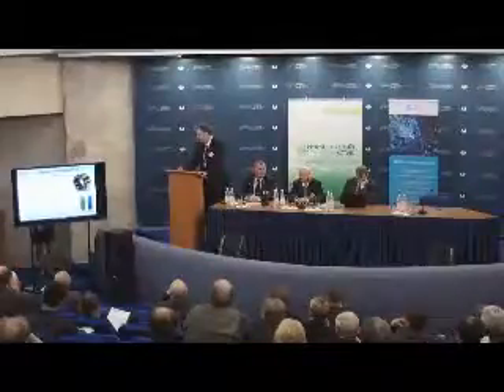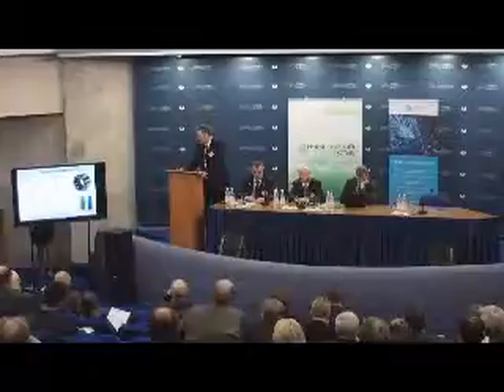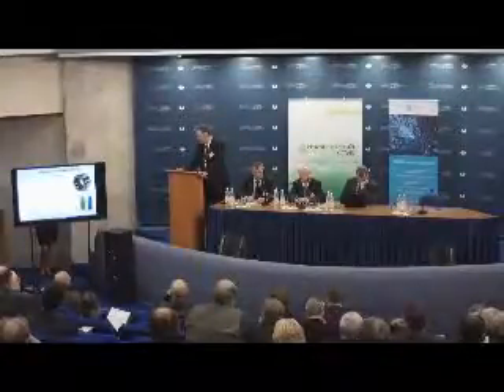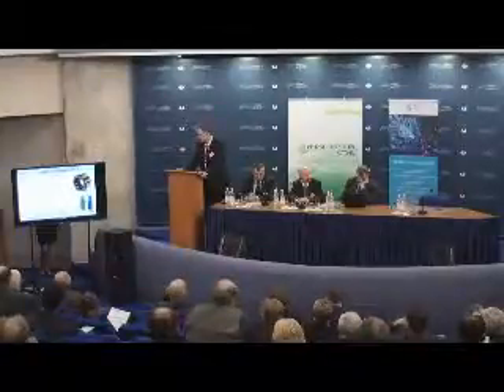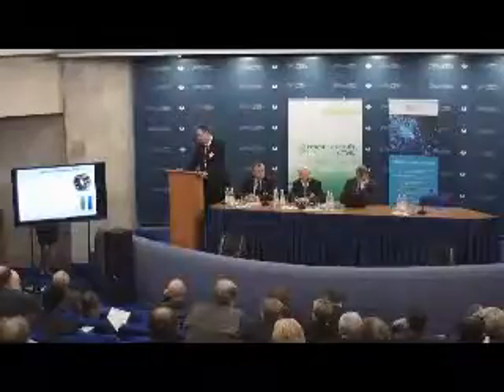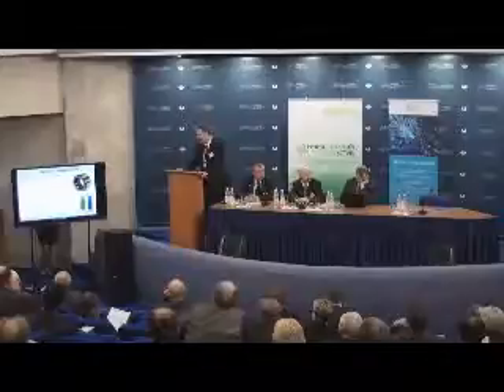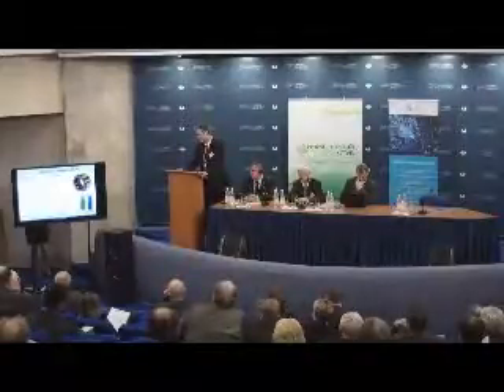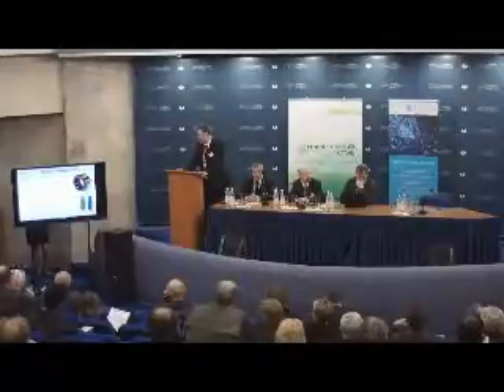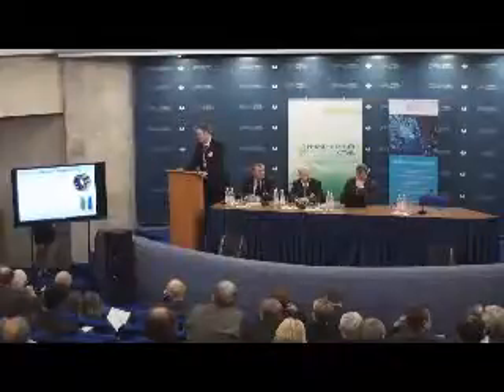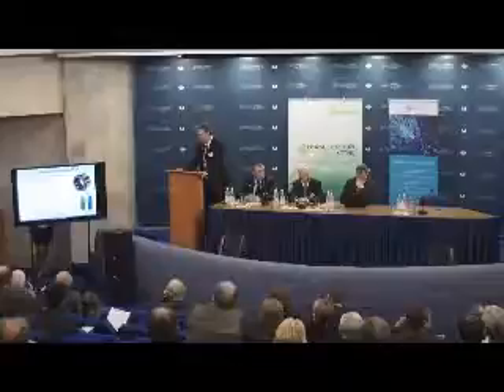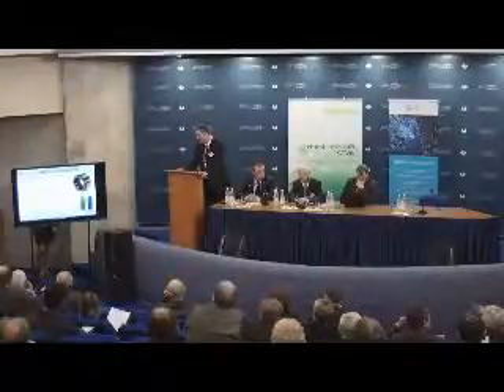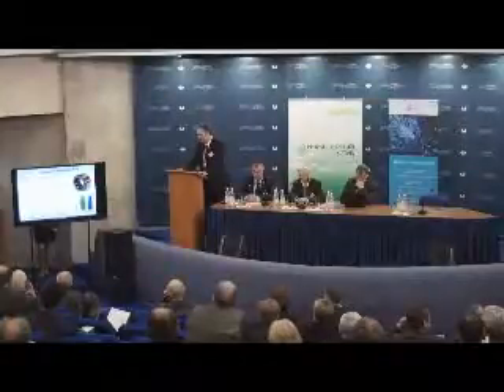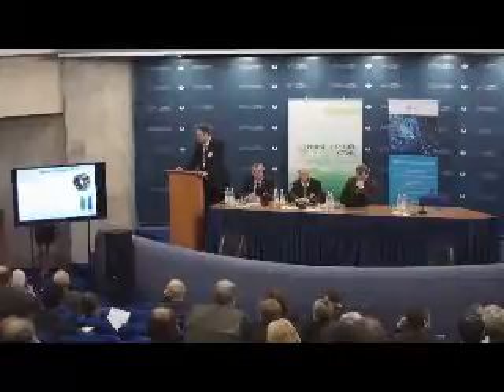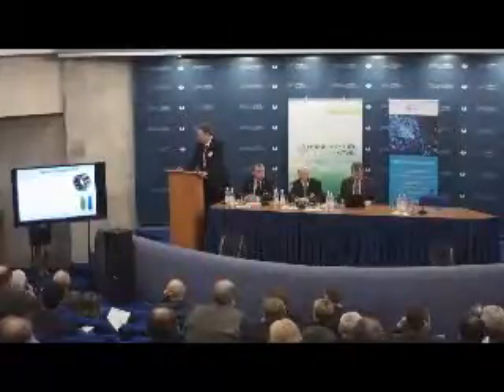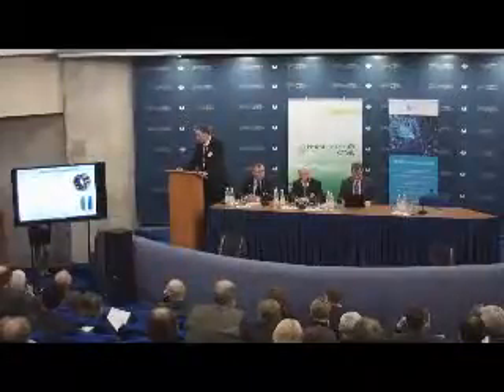So I wanted to take up one application which we have lately had success in. It's using ALD as a diffusion barrier against corrosion, and we had a 3-year-old project with the EU and several large corporations in automotive, aerospace and gas industries, and we have been able to develop a coating called Coral, which is reaching 600 hours in salt mist spray test, and the standard in the automotive industry is 192 hours. So we are already in production with this application. This is something that we have also utilized the nanocluster in Finland to help in developing.